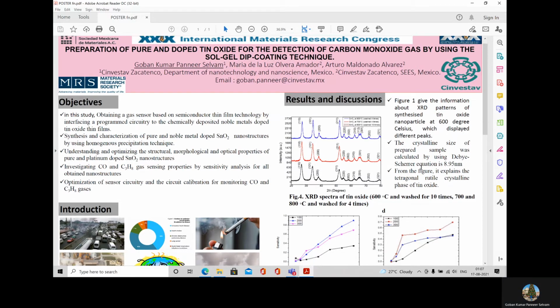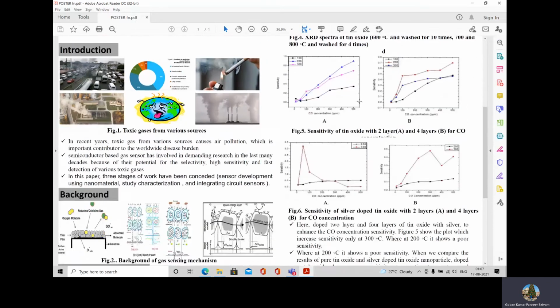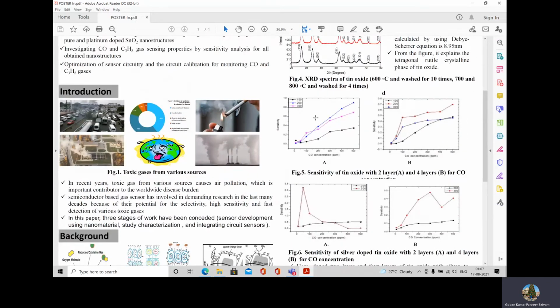In the next slide, I'm showing the sensitivity characterization of tin oxide with a 2-layer and 4-layer. If you see, the response change depends upon the temperature. At a particular temperature, we get a maximum result. For example, at 200 degrees Celsius, it shows the maximum result in 2-layer. In 4-layer, it shows a high sensitivity. Comparing 100 ppm, the 200 degrees temperature has a high sensitivity.